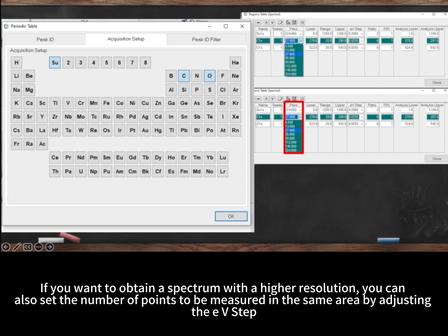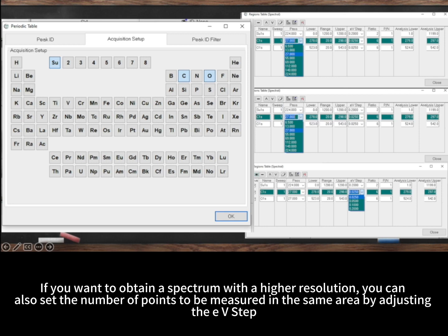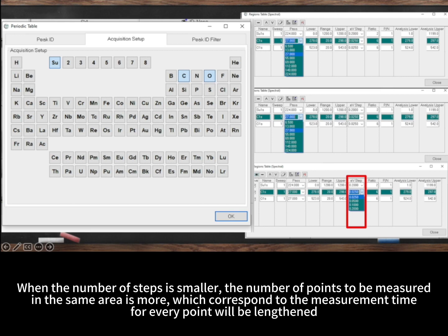If you want to obtain a spectrum with a higher resolution, you can also set the number of points to be measured in the same area by adjusting the eV step. When the step is smaller, the number of points to be measured in the same area is greater, which means the measurement time for every point will be lengthened.